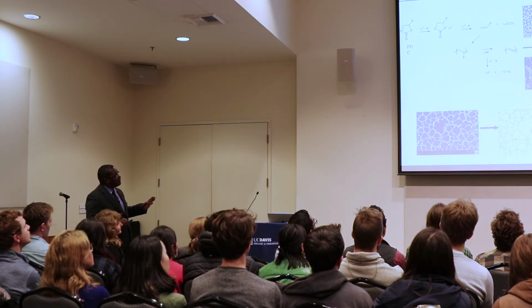So we did that, and this is what the results look like. We didn't use the lithium fluoride per se, but a salt that decomposes to form lithium fluoride on the electrode, because we wanted it to be completely uniform so as not to interfere with the model.